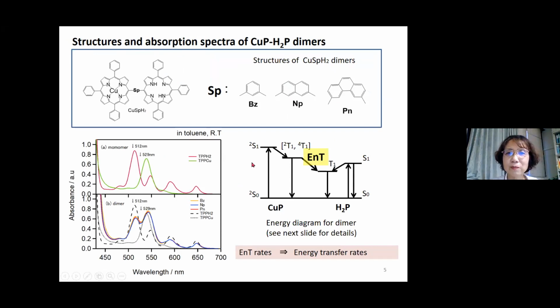So the free base porphyrin has a little bit lower excited state than the corresponding copper porphyrin. The lower column shows the absorption spectra of the dimers, and the copper porphyrin, free base porphyrin dimer shows absorption spectra which are almost coincident with the superposition of the monomers. So we can say that the electronic structure of the excited state is not perturbed very much.